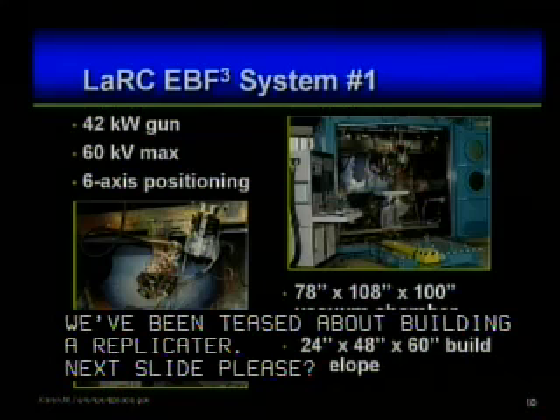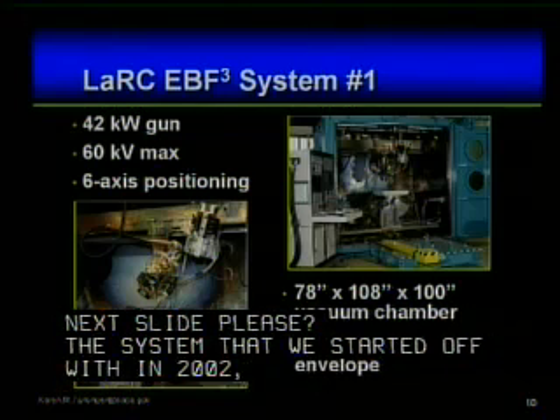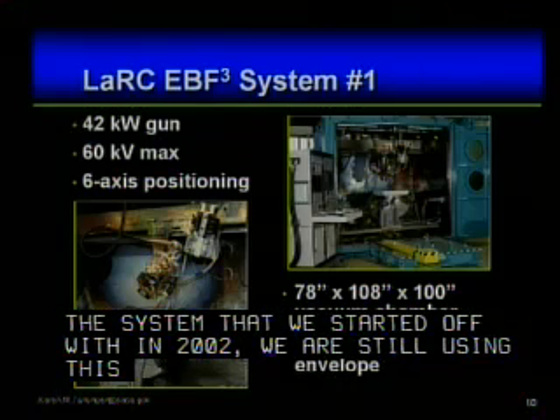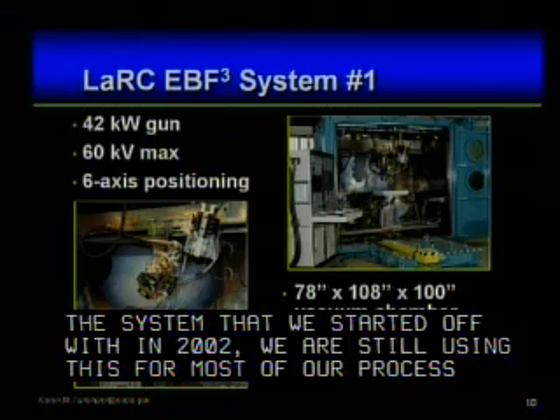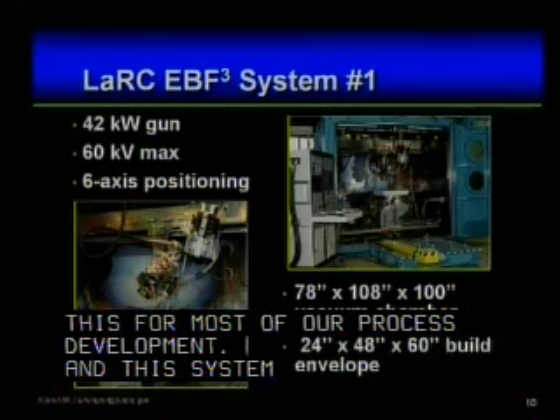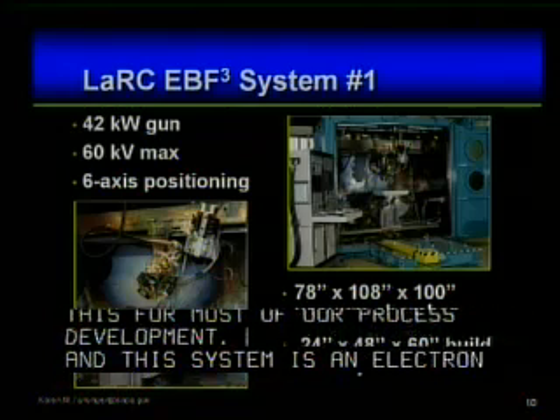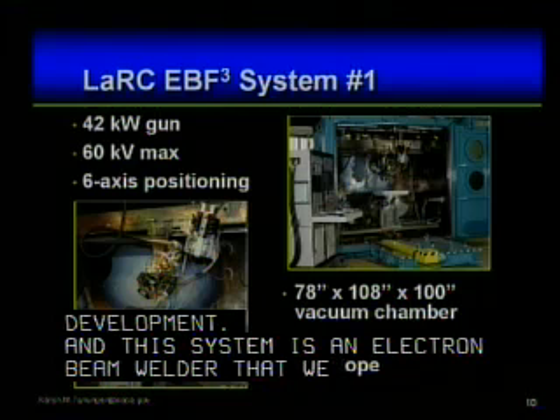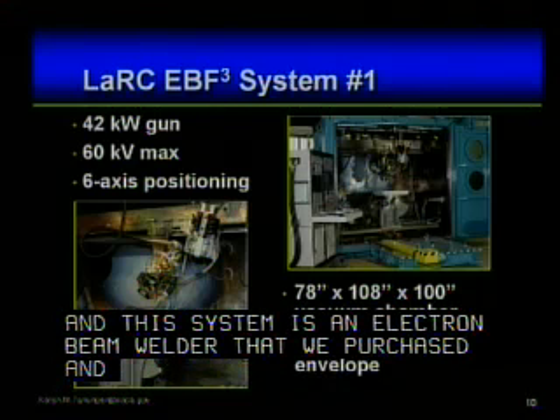The system that we started off with in 2002, we're still using this for most of our process development for our large fabrication experiments. And this system is an electron beam welder that we purchased, and we had it modified, adding a double wire feed so that we could build the layers up. It's got a high power electron beam gun.